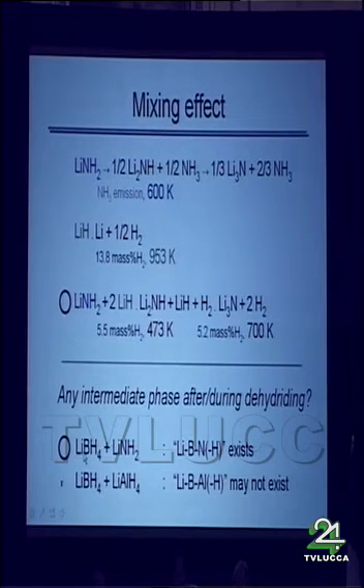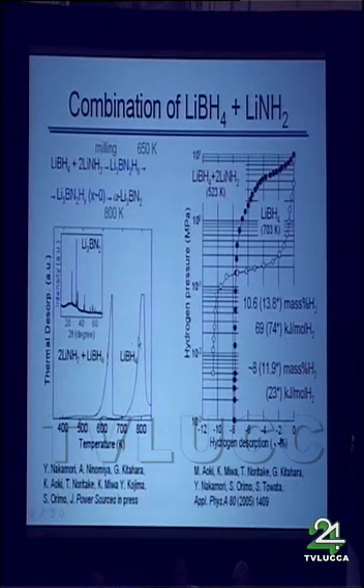Now, we focus on the combination of lithium borohydride and lithium amide. In this case, we have confirmed that the dehydriding temperature decreases so much, by more than 200 Kelvin, and also the dehydriding rate increases by one order even at lower temperatures. Apparently, lithium borohydride was destabilized by the mixing with the lithium amide system. Also, we have focused on this intermediate phase, the lithium BNH system, for realizing reversible dehydriding and rehydriding reactions.